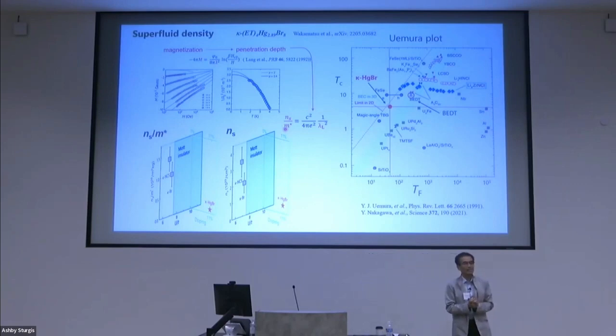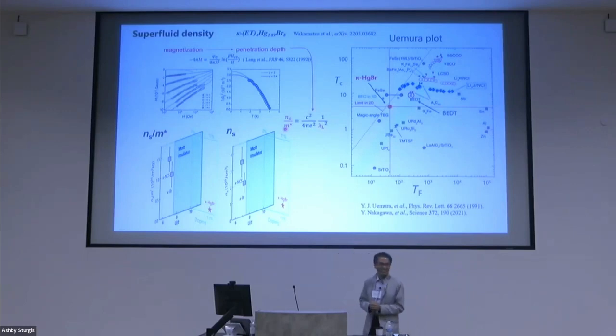Is it possible to measure quantum oscillations? We tried, not in vain. We cooled the sample down to 10 millikelvin, but we did not succeed in observing the Fermi surface. We wanted to do that, but all of this is indirect. I think that we should observe the Fermi surface, and then the large Fermi surface.